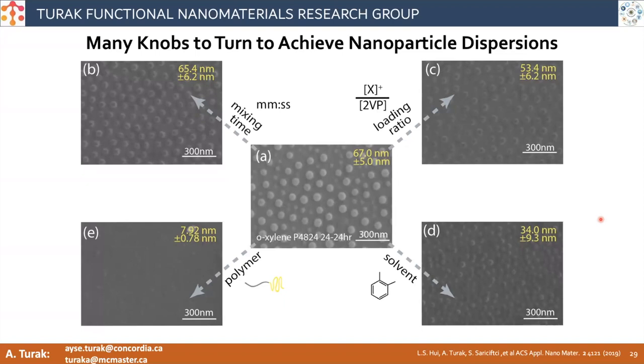So there are many knobs that we can turn to achieve these different kinds of nanoparticle dispersions. You can do things like change the mixing time, the ratios, the amount of solvent to polymer, right? All of these different things have an effect on the size of the nanoparticles, the size of the micelles, their distribution on the surface. By changing each of these parameters, you can achieve a huge landscape of different types of particles with different dispersions and different sizes.